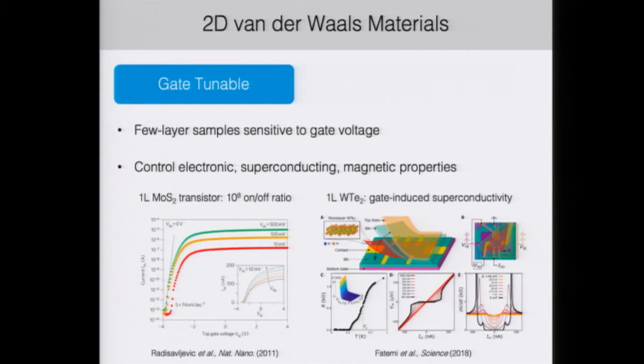They're very gate tunable. If you take a 3D material, such as the cuprates, and you want to change its properties, you generally have to dope it by substituting one type of chemical atom with another one. However, with 2D materials, since they're so thin, they're very susceptible to gate voltage, and so you can control their electronic, superconducting, magnetic properties, and so forth, just by applying a gate voltage. Then you have a very tunable device, rather than having to grow a series of different crystals with different stoichiometries.